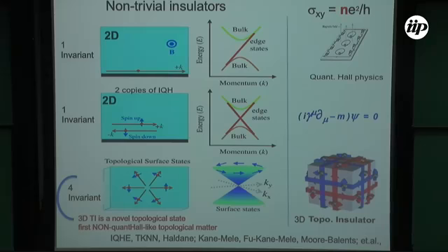So if you take this setting and consider the dispersion relations of the electrons involved and plot that in energy-momentum space, you'll see that the bulk bands have a gap, a band gap, that's why it's insulating, but on the boundary it's conducting, so there is a chiral edge state. There is a K plus state, but there is no K minus analogous state. So in other words, the energy-momentum space, or dispersion relation, of these electrons in this quantum Hall state is represented here. This is another way of representing this thing. There is an edge state, a chiral edge electron, moving in one direction.